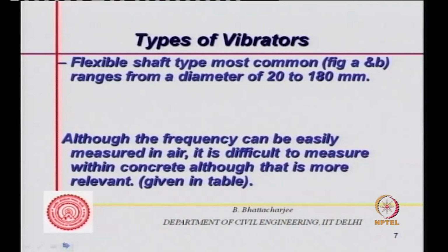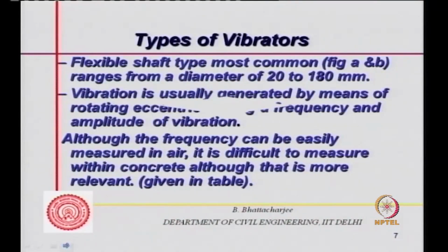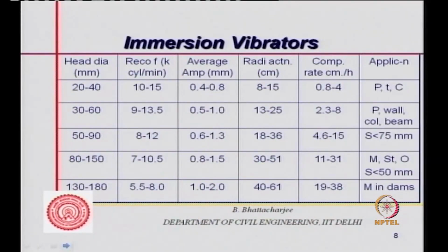This flexible shaft type is the most common, and its diameter can range from 20 millimeter to about 180 millimeter. Usually vibration is generated by means of a rotating eccentric, as we said, having a frequency and amplitude of vibration, and data on frequencies etc. is available. So dimensions are from 20 to 180. Now we can look at the head diameter of this needle, 20 to 40 mm.